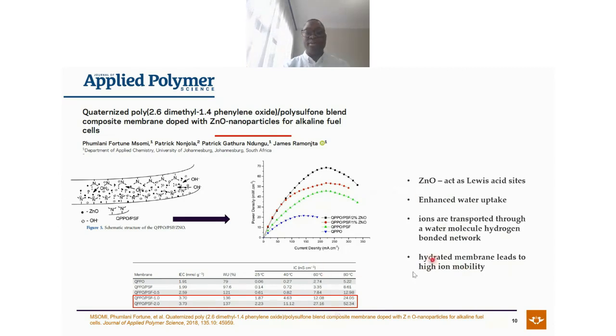Well, we look at the membrane that we've made. We look at the power performance of it. Then we did a comparison. As you can see here, the 1% and 2% zinc oxide membrane was able to give out, at 80 degrees, an ion conductivity of about 24 to 52. And during that time, remember, this paper is a 2017 paper. During that time, this was one of the highest ion conductivities that you get at this temperature.